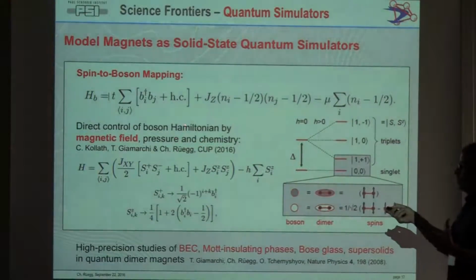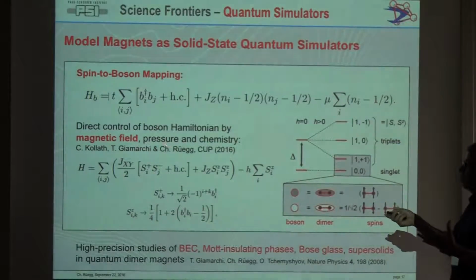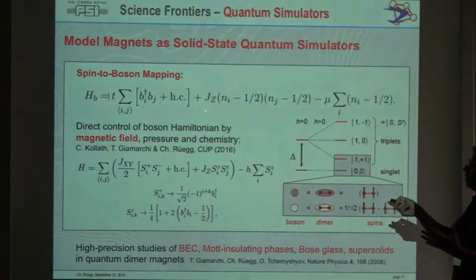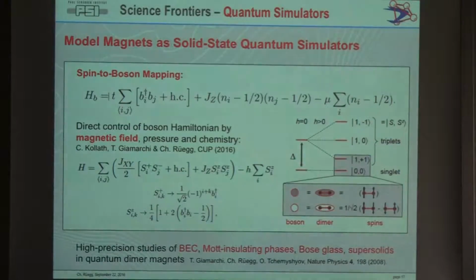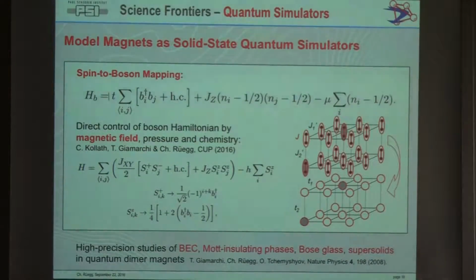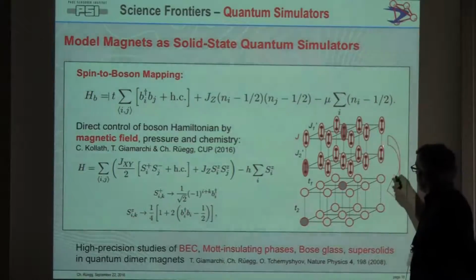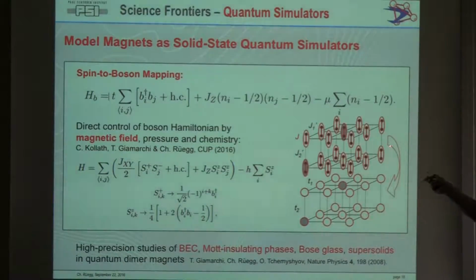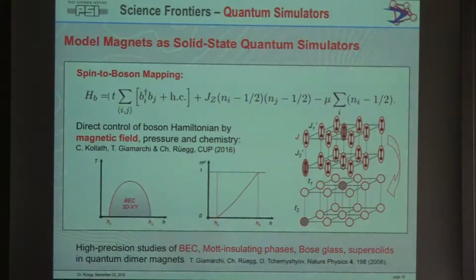And then if you have a real material, you can apply magnetic field, you can apply pressure, or play with the chemistry and have access to controlling these individual particles. So one of the phenomena we studied is BEC. You essentially come from a lattice of these dimers, and then you transform it to an effective particle picture. If you have a site which is in a singlet state, that's the vacuum state in the lattice. Whereas if you have an excited triplet, then you have a particle here and that hops around. And we have shown that this in a magnetic field can lead to a BEC.